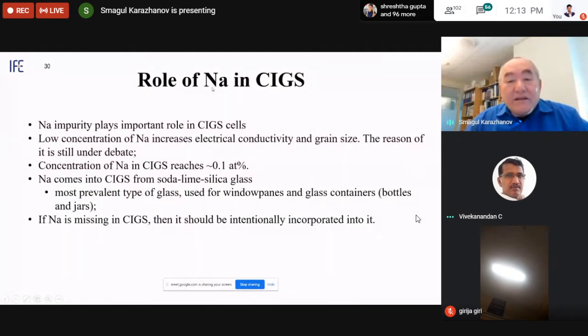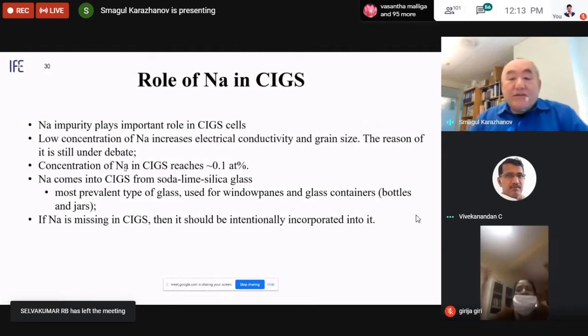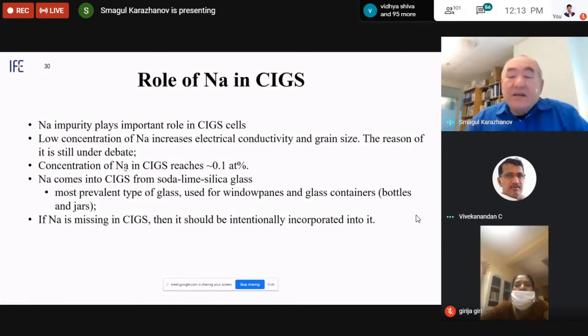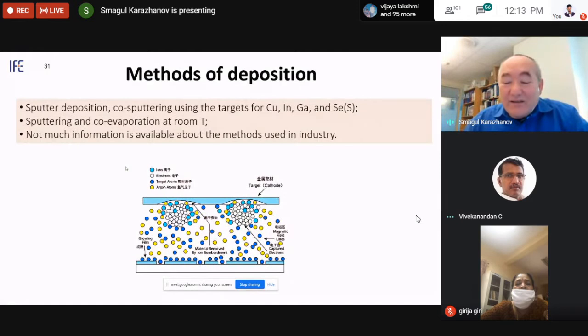And the challenge here is about sodium. Sodium should be present in the material to possess certain electrical conductivity and to control grain size. The reason is still not known. The sodium is coming from glass containers. However, in case glass is not used, then sodium should be incorporated. Otherwise, the solar cell cannot have as high efficiency.